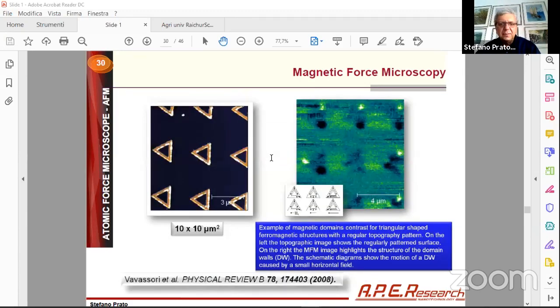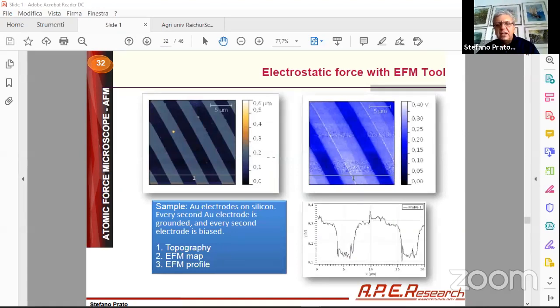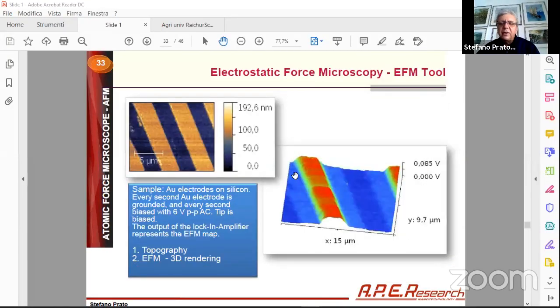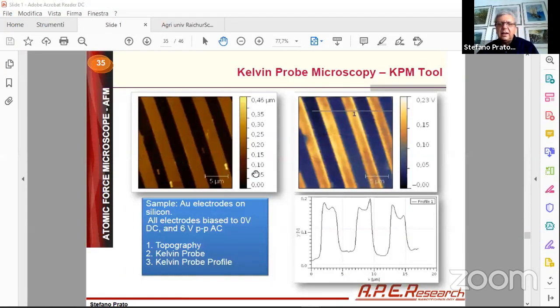I will go quick on this. This is quite nice. You can measure the electrostatic force. So if you have a sample like this, you can do the map, but you can also see how those are wired on top of silicon, conductive wire. Some of them are conductive, some of them are biased, some of them are not. You can see the difference. Okay, again here, Kelvin probe is an ancillary technique. So you have topography and you have Kelvin mapping. From the Kelvin mapping, in this case, the color is not a difference in height, but the color is a difference in material, okay? Every material has a different work function, and the mapping here is a mapping of the work function, okay?